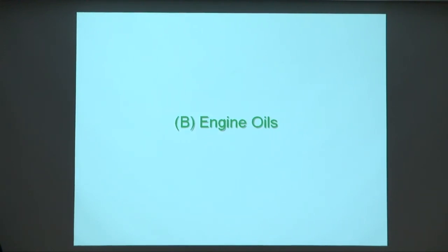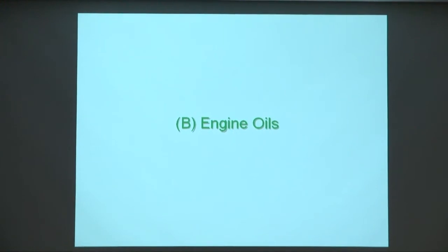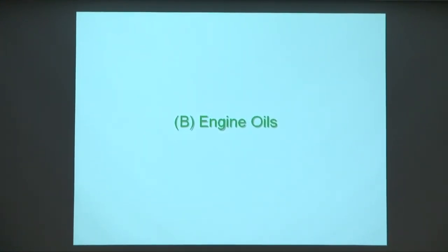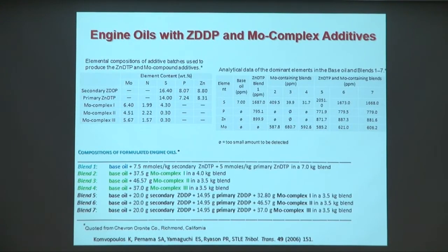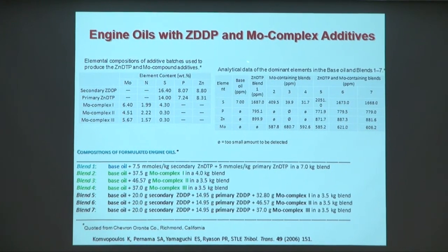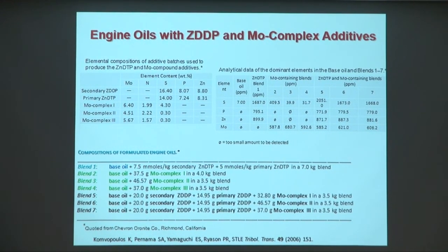So in addition to gear oils, we have engine oils, and here the specs are different. So we have to worry about these as well. How do we lubricate the engine? And here we will see that we can use molybdenum to replace the phosphorus and sulfur in ZDDP, the so-called molybdenum complexes. Molybdenum, again, can form a hard phase and therefore can take the role of at least phosphorus, reducing the amount of phosphorus, if not eliminating the phosphorus.